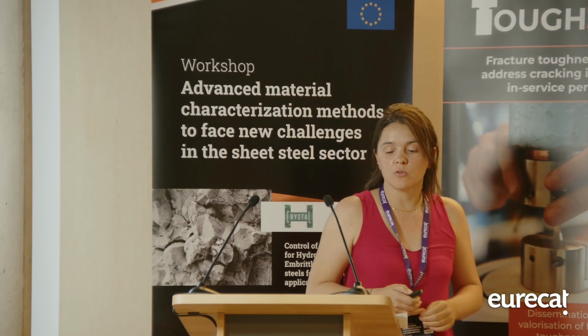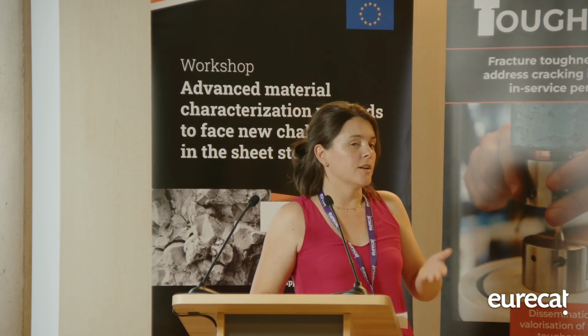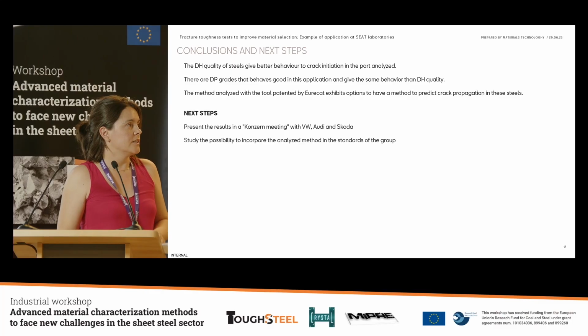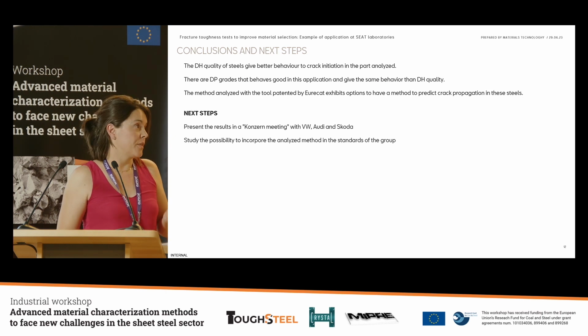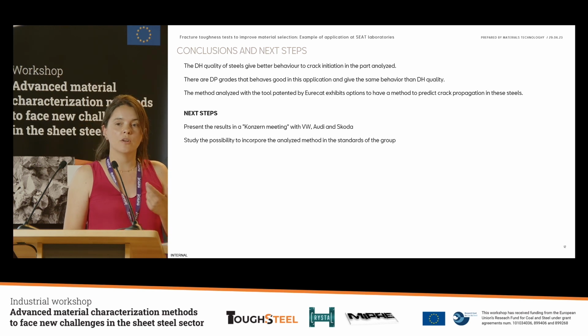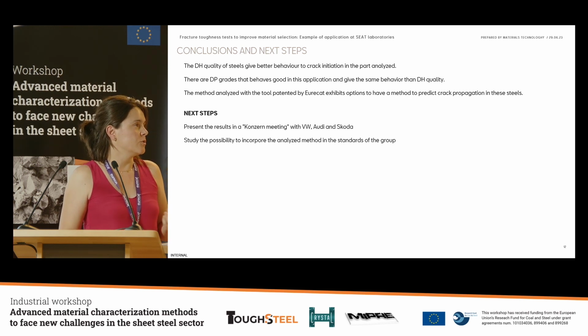Yeah, just the final conclusions for this study. We knew that the DH quality has better behavior in production, and we have found that with the fracture toughness it is also seen that the results are better. But with DP grades, we see that some coils also exhibit good behavior and good results in fracture toughness. So maybe this value is a good option to have in the specification in order to sort and to avoid these kinds of problems.